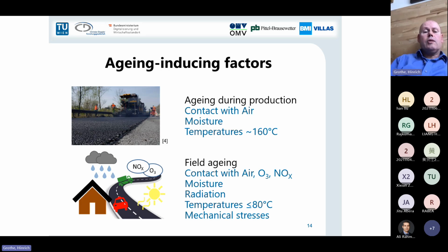Okay, so when talking about aging, we can differentiate 2 processes. The first process is the short-term aging. This is what happens just at the beginning. During the production, in the mixer, there's a lot of contact with the air, with moisture, but also the temperature is quite high. It's about 160 degrees during the production of the road. Later on, during the next 10 to 20 years, when the road is used, there's the so-called field aging.